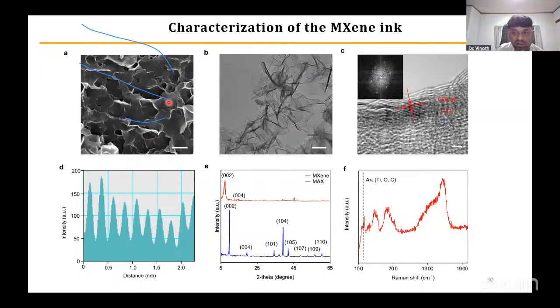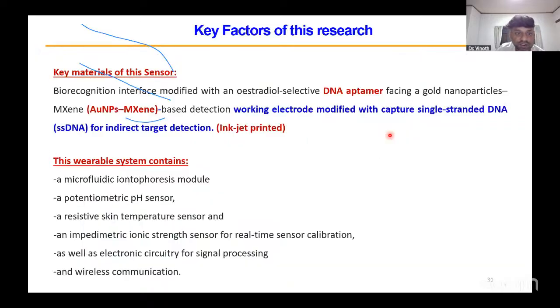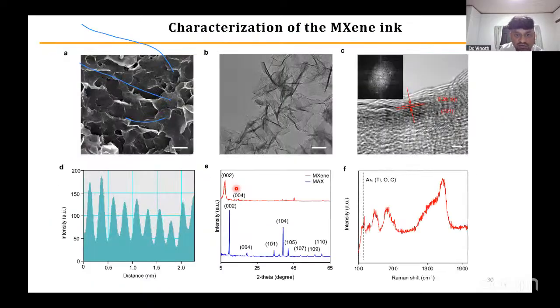These are the SEM and TEM images of MXene, along with XRD and Raman spectroscopy, confirming the MXene and the formation of MXene from the MAX phase. Also, this is the crumpled sheet-like structure of MXene ink. The key factor of this sensor electrode is the biorecognition interface modified with estradiol-selective DNA aptamer, combined with gold nanoparticles and MXene as the working electrode, with a capture single-stranded DNA for indirect detection. This wearable sensor device contains a microfluidic iontophoresis patch, pH sensor, temperature sensor and impedimetric ionic strength sensor, as well as electronic circuit and wireless communication, as we saw previously.